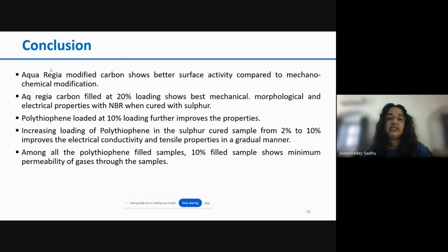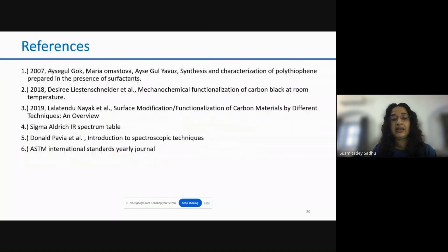Increasing loading of polythiophene in the sulfur cured sample from 2% to 10% improves the electrical conductivity and tensile properties in a gradual manner. Among all the polythiophene filled samples, the 10% filled sample shows the minimum permeability of the gases.